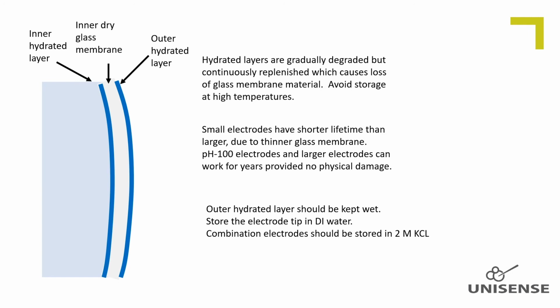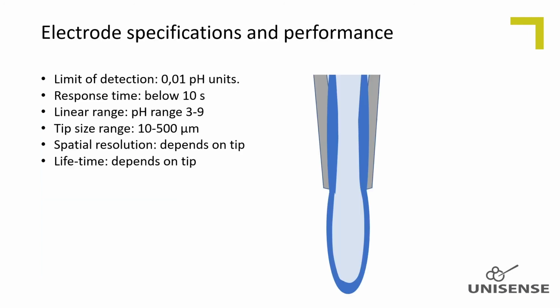Combination electrodes should be stored in 2 molar potassium chloride. Unisense pH electrodes are made for high time and spatial resolution pH measurements, where larger and more robust electrodes cannot be used. Thus, the long-term drift of our electrodes is not as well characterized as larger standard electrodes from other suppliers. The drift will typically decrease over time and will typically be within a few millivolts per week. We recommend, however, to calibrate as frequently as convenient for all important studies.